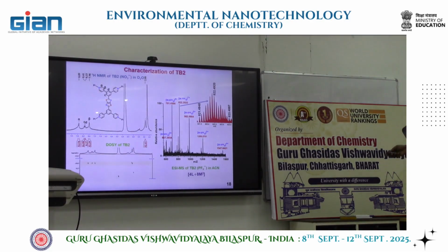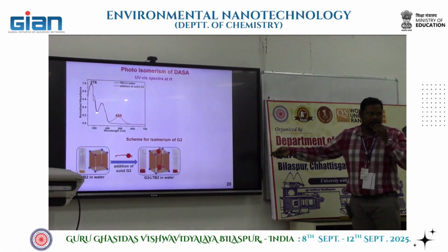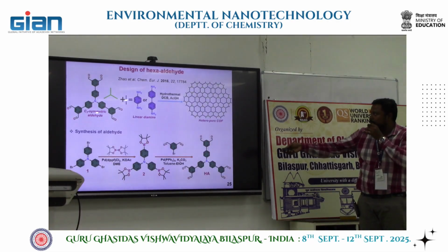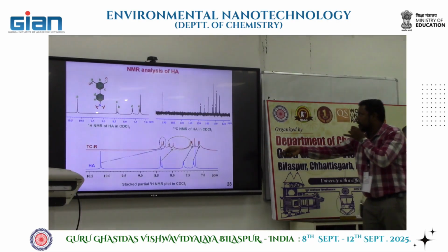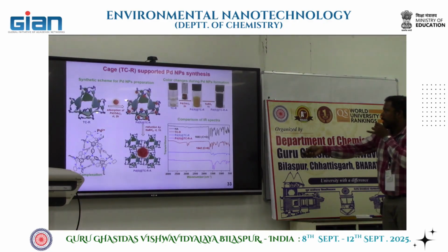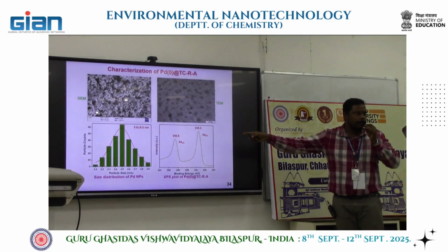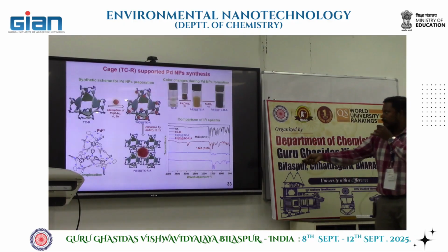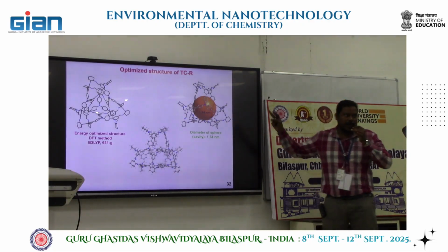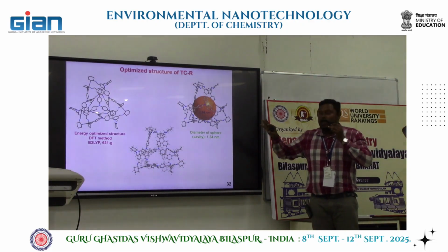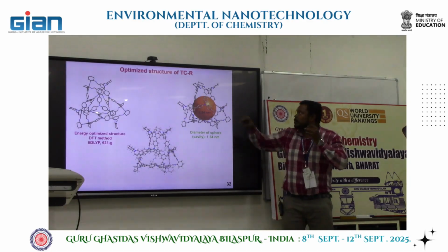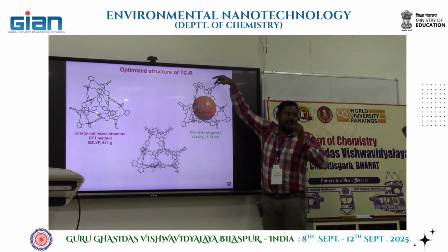Right, sir. Actually, we thought that the nanoparticle would form inside the cage pocket, but we did not see that. That is a good observation, sir. The nanoparticle size, if you see, is 3.5 nanometers, and the diameter we calculated by DFT is 1.24, if you consider a sphere. So it is actually multiple cages supporting the nanoparticle. It forms at the vertices, because the vertices have the complexation unit.